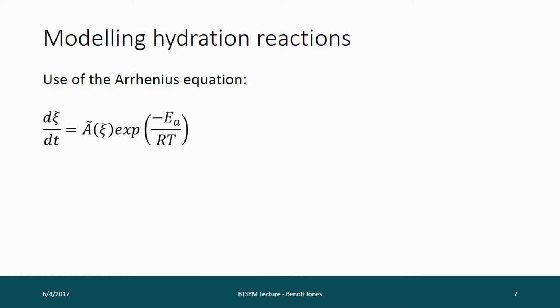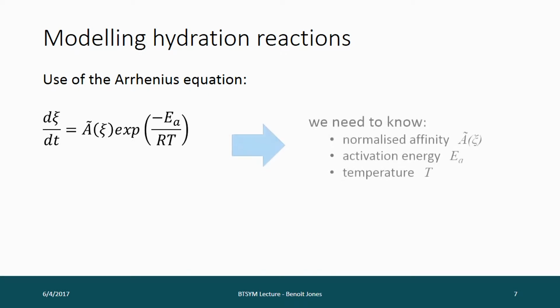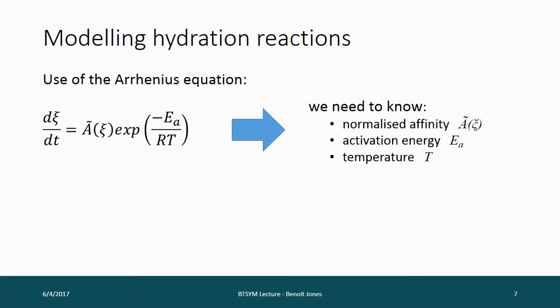So you've got rate of hydration is equal to the normalized affinity, the A tilde, which is itself a function of degree of hydration, multiplied by e to the power of minus the activation energy, EA, divided by R, which is the ideal gas constant, a universal constant, you look it up, and T is the temperature. So if we know the normalized affinity and how that varies with degree of hydration, and if we know the activation energy, which is the small amount of energy you need for a chemical reaction to occur, and if we also know the temperature at any time, then we can calculate the rate of hydration.